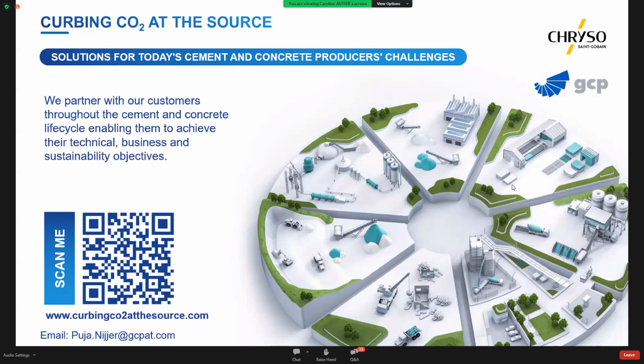Yes, because actually there are no universal additives allowing to treat all cement with the highest performance. As we explained, the product selection depends on different parameters like cement composition, technical requirements. So we gave the example of cement with calcined clay, but the requirements could be different, for instance, for a slag cement, because in this case, there are less issues with the water demand, and in this case, generally, the requirements are more focused on the early age. So it's a real case-by-case approach when we need to address a product to a customer.